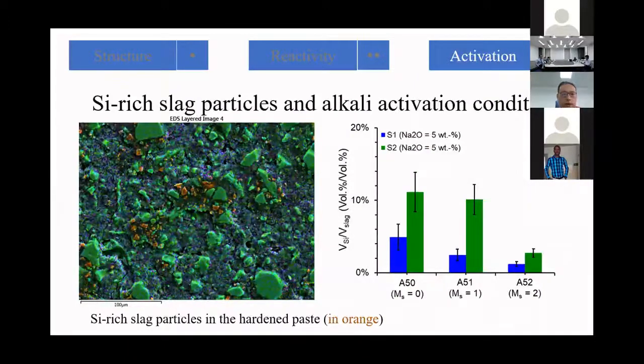In this EDX mapping method, we also found a phenomenon that some slag particles show silicon enrichment. We call it silicon-rich slag particles. The volume percentage of these silicon-rich slag particles is correlated with the alkali activation condition. Generally, with the increase of the silicate concentration, the volume percentage of silicon-rich slag particles decreases. It's reasonable because if the solution is saturated with silicate anions, the dissolution of the silicate from the glass phase will be inhibited.